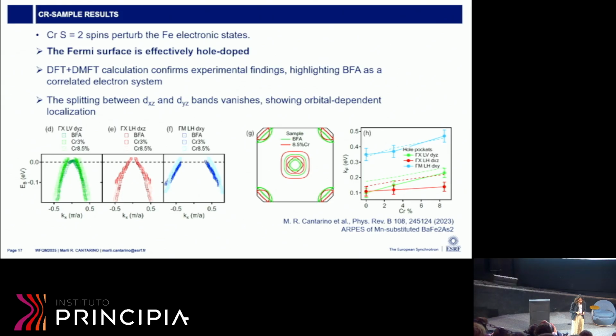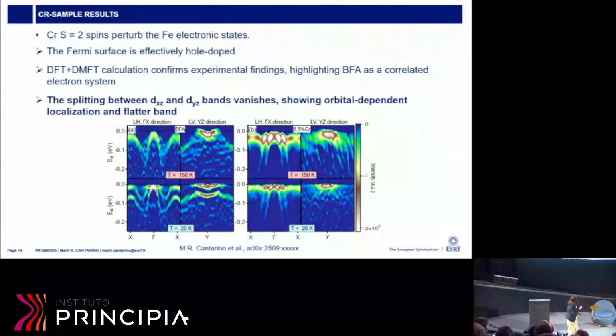We see that the band splitting that we saw in the parent compound and in the manganese compound is not there anymore, and this band specifically that goes to the hole pocket is much flatter. So in this case, there is this orbital-specific localization and flatter band that aligns to a picture where the effective hole doping is bringing the system towards a more localized state.